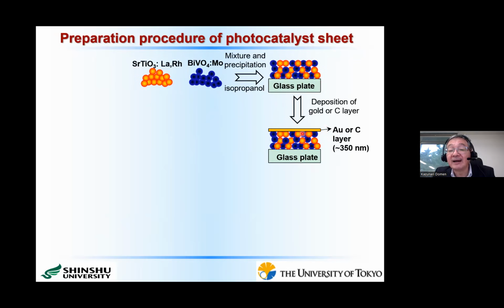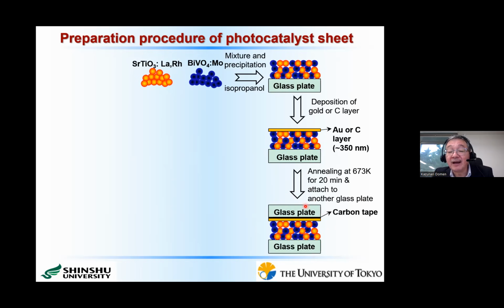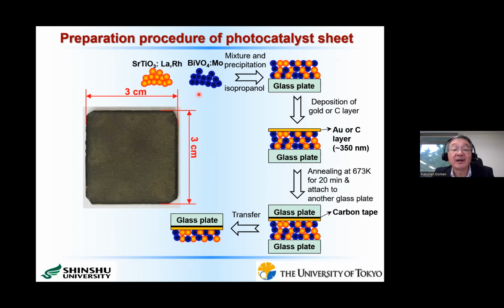Then, after annealing at some temperature to make the layer stick better to these photocatalysts, we put on another glass plate. In this case, this glass plate has double-sided carbon scotch tape. So we push, then peel off, and we can get this kind of structure. After removing the remaining physisorbed particles by ultrasonication, we can get this kind of photocatalyst sheet prepared on a glass plate. In this case, the size was about 3 centimeters by 3 centimeters.